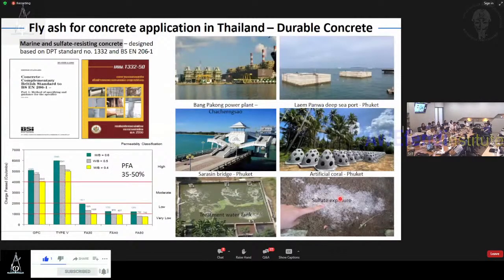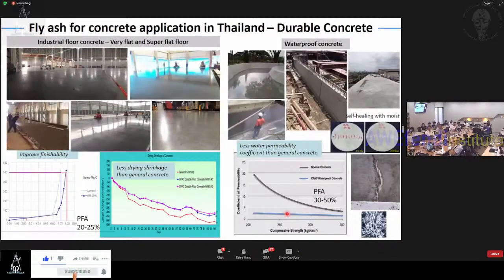This is a project where we use fly ash for marine environment and also sulfate environment. And as Professor Smith mentioned, we have our own performance-based standard guideline for the design of durable structures in severe environments. So the benefit of fly ash is that it can resist chloride very well. Chloride penetration is going to be low when you replace more with fly ash and reduce the water cement ratio. This is some projects in Thailand, and also sulfate resistant ones as well: some water treatment tanks and some soil that has sulfate conditions. This is a benefit of fly ash for durability.